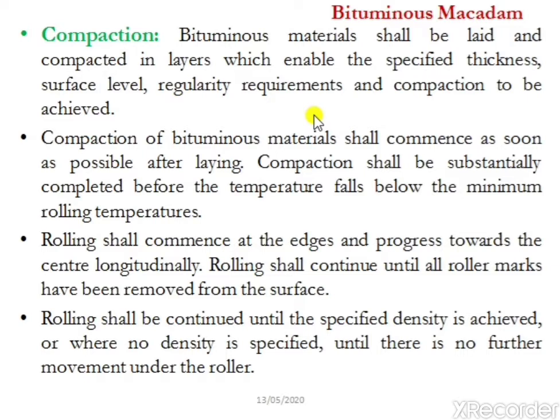Rolling shall be continued until the specified density is achieved, or where no density is specified, until there is no further movement under the roller. So the operation of rolling should be continued until the specified density is obtained. When the contract is signed between the government agency and the contractor, they will specify each and everything. Like that, for compaction also they will specify the density in the agreement, so rolling has to be done until that specified density is achieved. Suppose there is no specification for the density in the contract, then the rolling should be done until there is no movement under the roller.